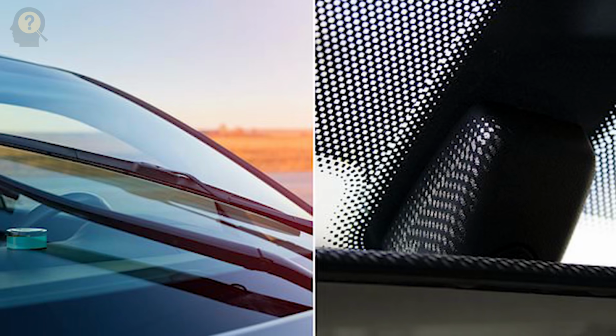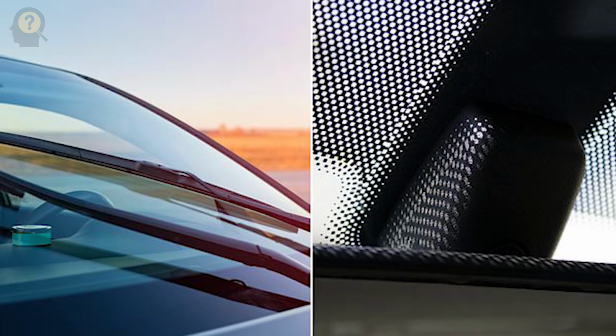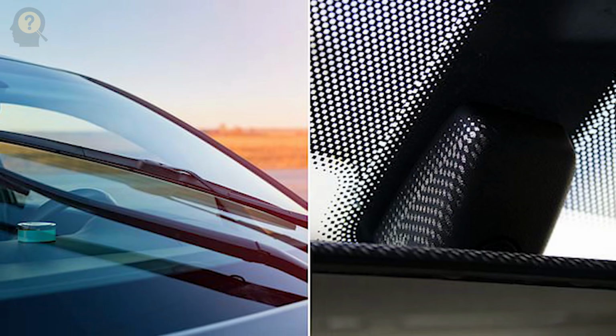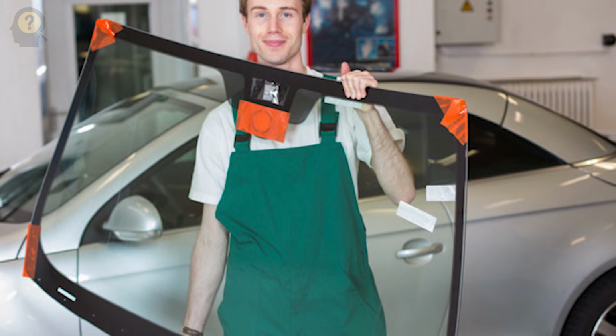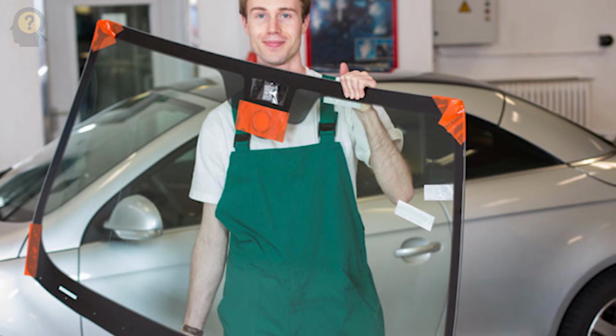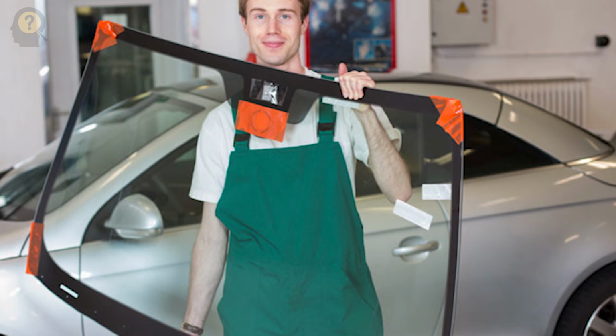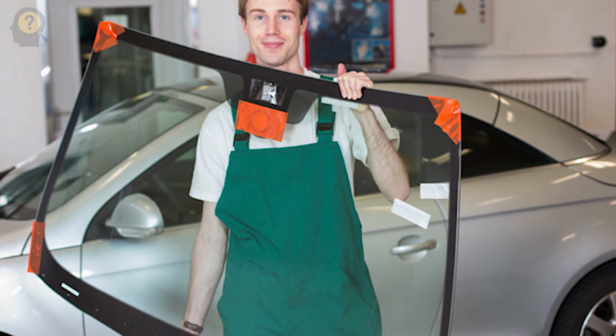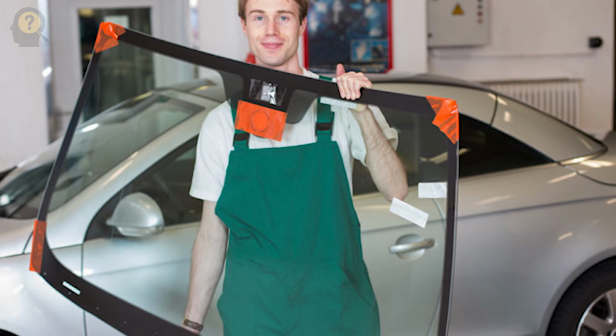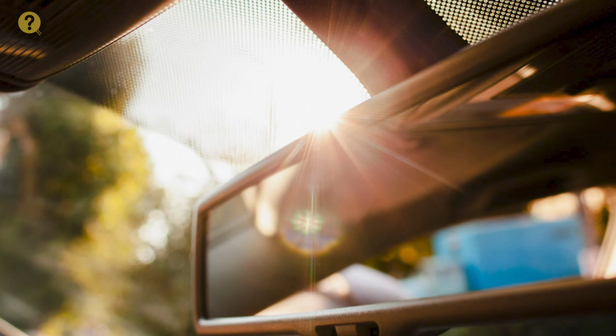Interestingly, the manufacturer didn't change the material. They didn't add a buffer strip. They used the ceramic dot pattern itself as a thermal gradient, a way to gradually disperse the temperature change instead of having it impact all at once. You might think the solution to the heat problem would involve adding something. It turns out the answer lies in reducing the space.